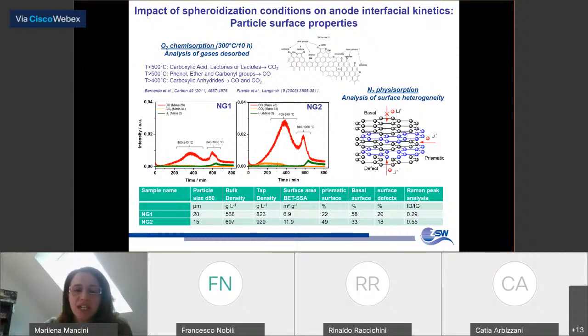And here you see that there is a big difference between the two samples of natural graphite in terms of release of oxygen-rich gases, which means that by changing the parameters of spheroidization, you get completely different surface chemistry. And another method we have applied to analyze more in detail the complex nature of the surface of the carbon is to analyze the surface heterogeneity in terms of share of defect, basal, and prismatic planes by using the results from nitrogen physisorption and applying DFT model